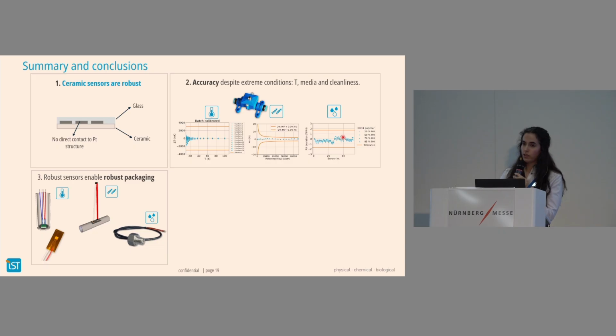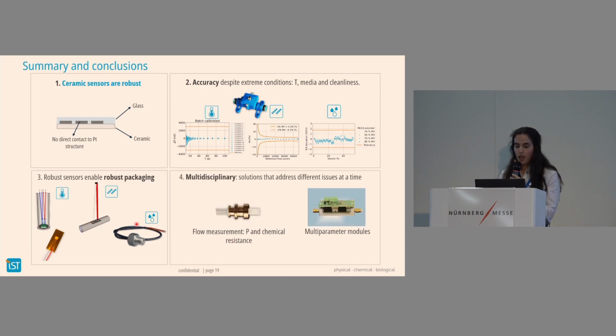We saw that in the case of temperature from this polyimide laminated solution, but also for temperature and flow, because it's possible to solder these sensors on top of a stainless steel surface, or because it's possible to make a probe out of it. And then last but not least, this robust packaging can also apply to the glass sensing. These are all multidisciplinary solutions, meaning that they don't tackle just one problem. They solve different problems at a time.